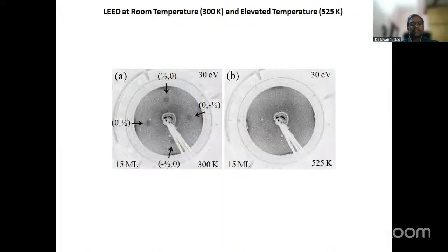And as you can see, the result of the experiment done on a 15 monolayer nickel oxide film, you can see that at room temperature you can find the half-order spots. These are the half-order spots, and when we heat up the sample, when we elevate the temperature, these half-order spots vanish because the sample crosses the Néel temperature. So the sample transits from the antiferromagnetic to the paramagnetic phase.